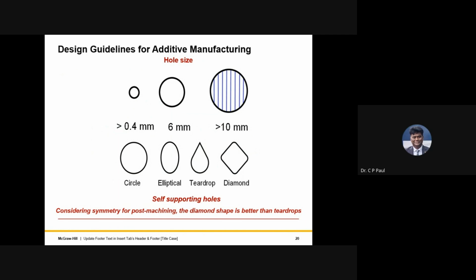If you are making a component and in the component there are different holes, more than 0.4 millimeter, you don't need any support and they go very well. But if you are making anything which is less than 0.4, we need to take some precautions while making metallic additive manufacturing component so that the hole comes properly. 6 millimeter not required, but any hole which is more than 10 millimeters, you need to give support structure in general in the design aspect, so thing can be done.